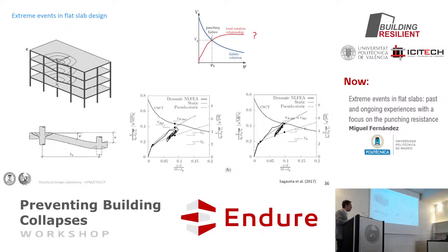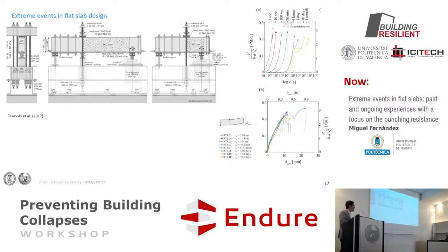So now, of course, all the discussion happens in this, and I want to show also some tests, just to show that this is really what's happening, or I feel that this is really what's happening. We did some tests in Lausanne that were very similar to the test of Sagaeta, but in one-way shear. So these were beams in shear, not slabs in punching, where we were loading these beams up to failure, varying between 1 second and some weeks.